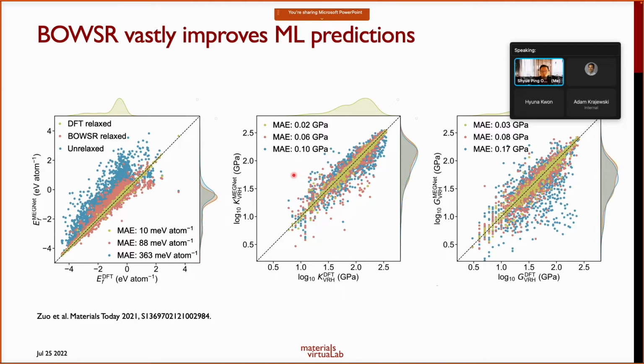Now, what we showed was that by just such a simple concept, applying the variational principle with our energy model, we can significantly improve the machine learning model predictions, right? So this is the predicted formation energy, bulk modulus, and shear modulus, log of the bulk modulus and log of the shear modulus for unrelaxed crystals, in which we just take the initial structures from experiments that are not relaxed. We use the BOWSR relaxation, and we also did DFT relaxation on the crystal structures, right?